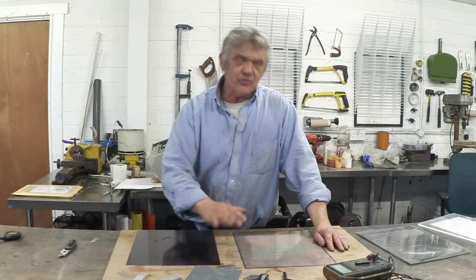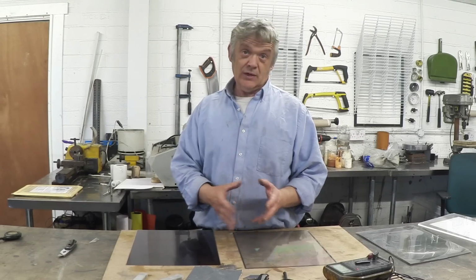This glass, incidentally, that this is on also is actually really expensive glass. It's not normal glass. It's an optically pure glass with a low sodium content. So try not to break them as you separate them. But if you do break them, don't throw them away. Cut them into little squares with a glass cutter and keep those squares, because those glasses that you've created actually have quite a lot of value and will in themselves cost you a lot.